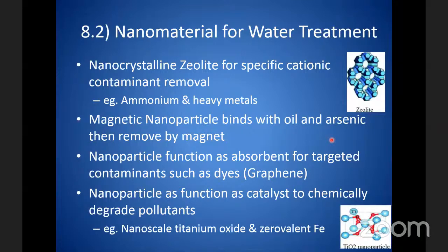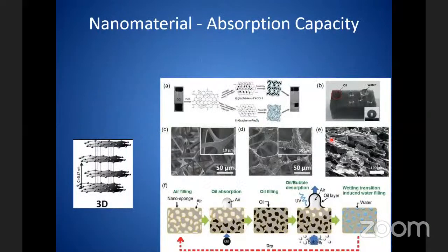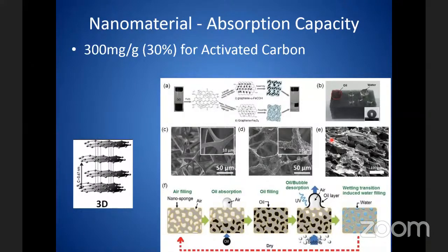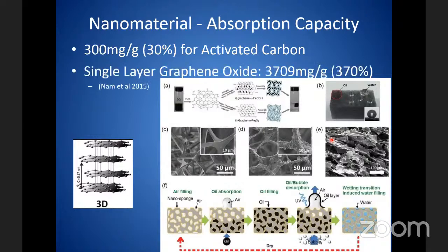So those are photo, titanium dioxide. So just for us to imagine, nanomaterial can be used as absorbent. Sometimes these absorbents are very high. For example, at the moment, activated carbon are normally the highest, in a very high range. We are talking about the so-called absorption capacity, which is 300 milligram per gram of activated carbon. So it's 30%. But for this nanoparticle, it's a single layer graphene oxide.